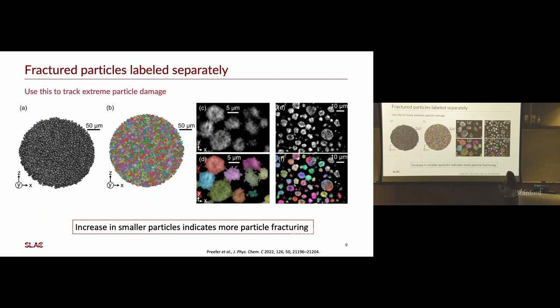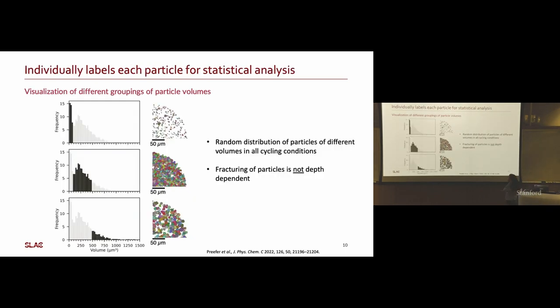And what you find if you're doing this labeling is sometimes you'll mislabel a particle that's cracked in half. And so the computer doesn't know that it actually used to be two particles. Your eyes can see it very easily. For example, this one's a great one. It's multiple particles, so it's cracked in multiple places. And we actually allowed the computer to do those false labelings because we wanted to see that if we have an increase in the number of small particles, that means more fracturing. So we used that sort of mislabeling to help us determine how much fracturing we have in our particles, in our electrodes. And so here's plots of frequency.